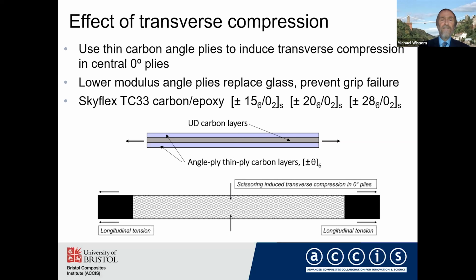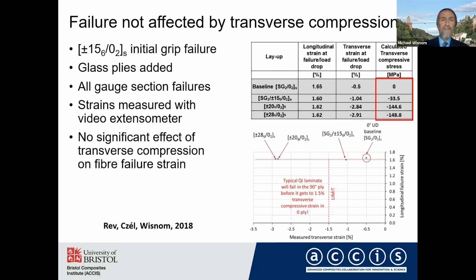And in this case here, those lower modulus angle plies, although they're carbon now, they still have a similar function in that they shield the zero plies from the stress concentration at the grips. So again, we get gauge section failures rather than failure at the grips. And we've done this with plus or minus 15, 20, and 28 degree laminates. In fact, the plus or minus 15, we did get some grip failures, so we had to put some glass on those as well, but the others were just carbon, all carbon laminates.